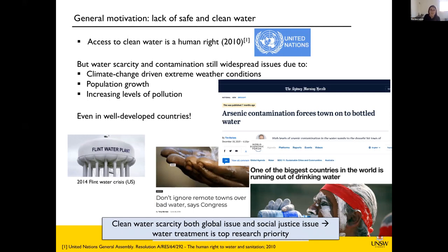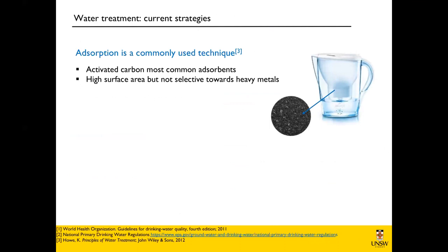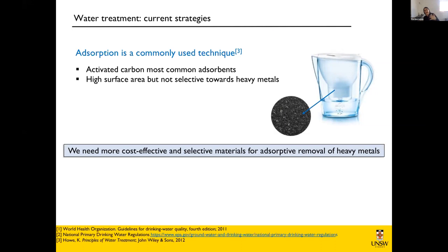There are a bunch of technologies that we can use to deal with water contamination. One of the most common is adsorption, where we essentially expose the contaminated water to an adsorbent, such as activated carbon, so that the contaminants are trapped and the clean water can get through. This is, for instance, the technology used in the water pitchers a lot of us have at home. But unfortunately, adsorbents like activated carbons are not specific to target certain contaminants, for instance, toxic heavy metals.